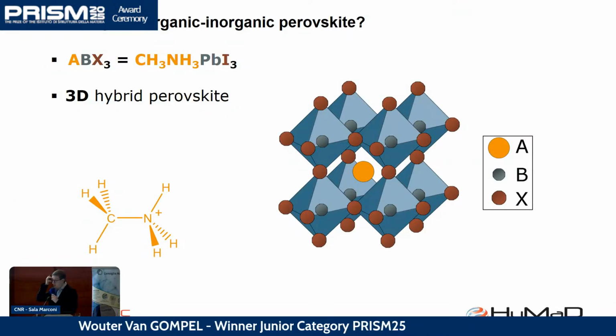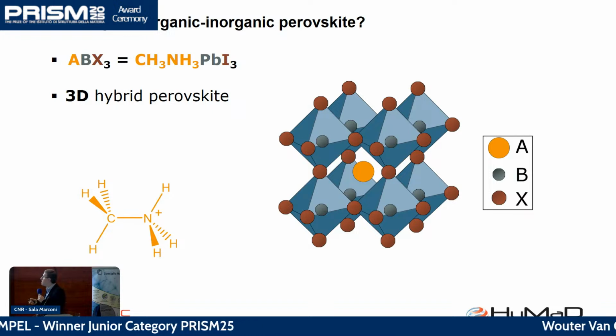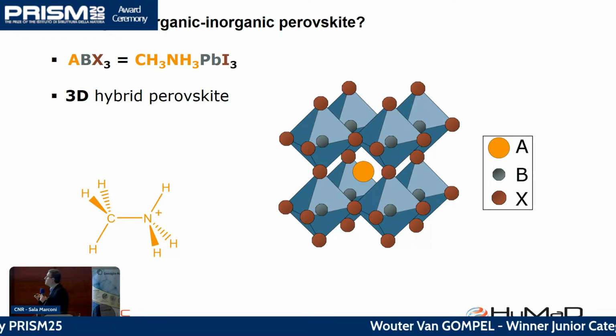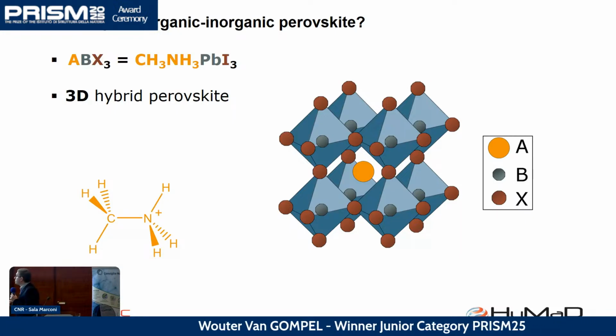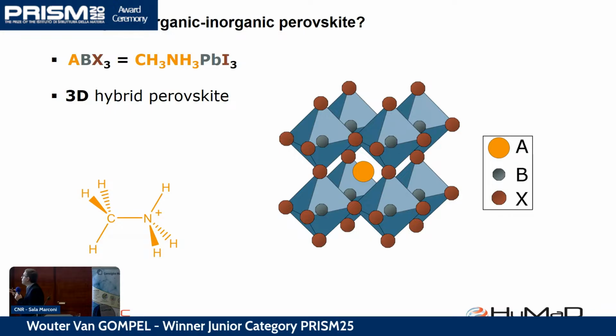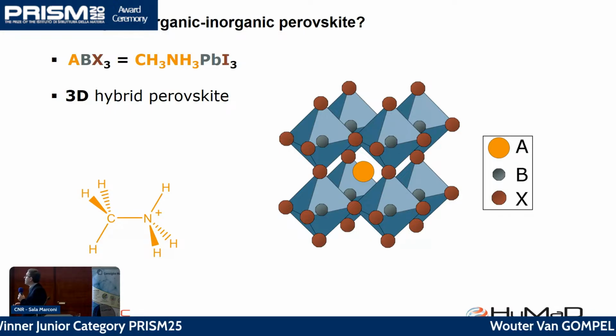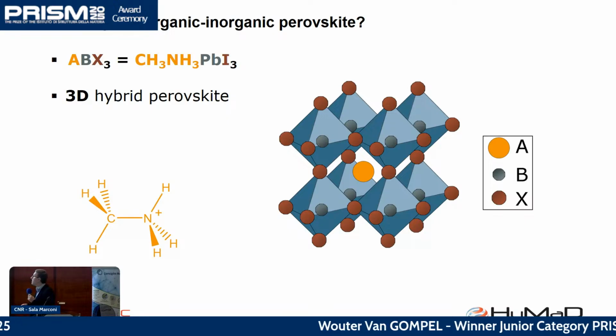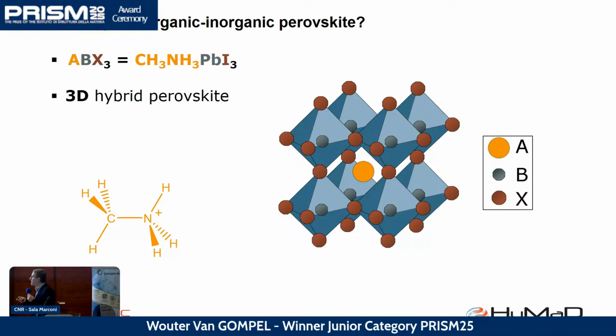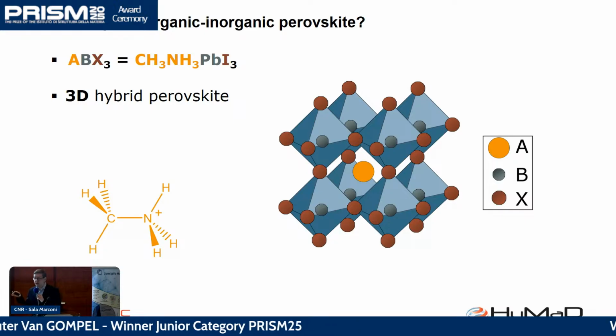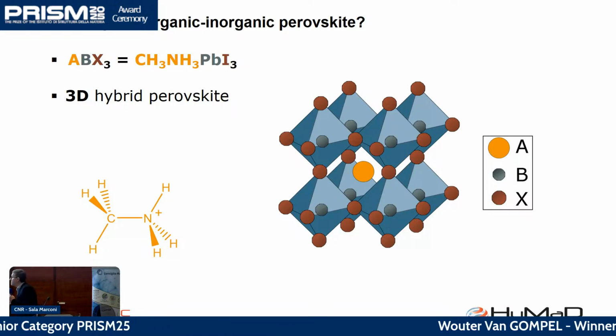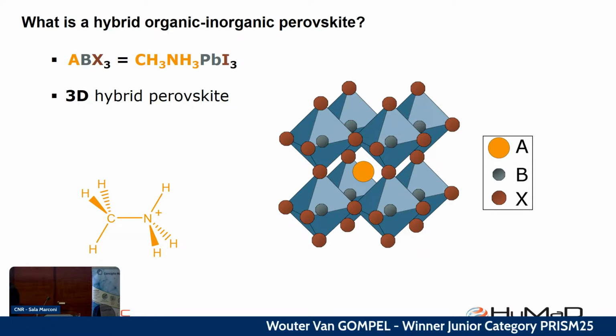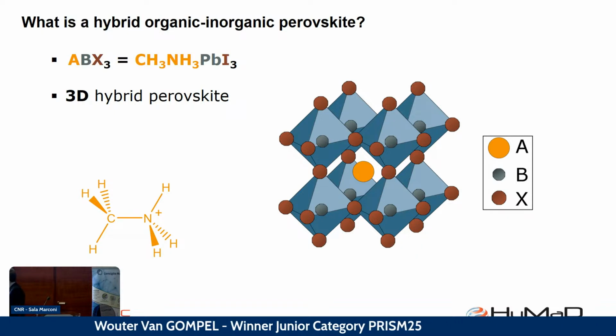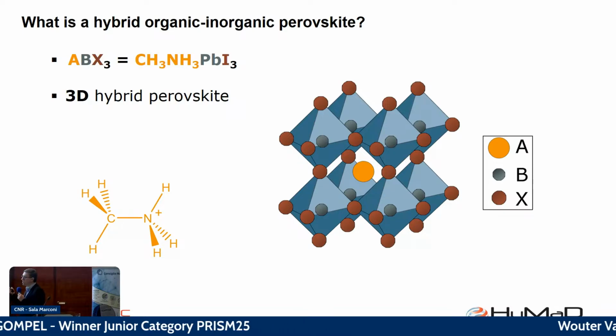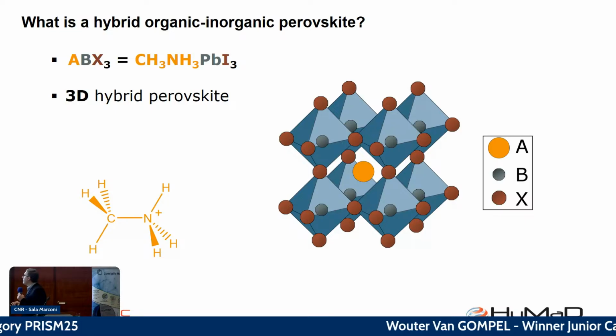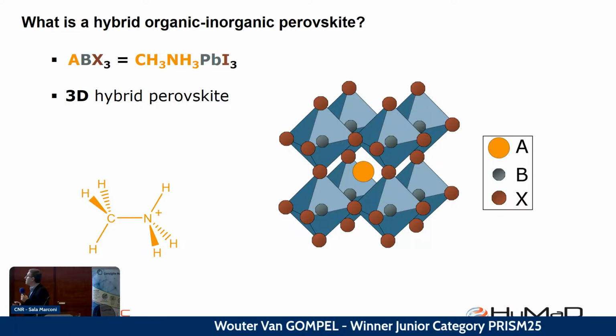So hybrid perovskites belong to the bigger class of perovskites. It's a very big class of materials which all share the same general formula, ABX3, with a well-known crystal structure composed of octahedra, with in general B metal ions inside of the octahedron, and then X ions at the corners of the octahedra, and in the middle you have a bigger cation, the A cation. In the case of the hybrid perovskites, the center cation is an organic molecule, typically an ammonium cation, like the methylammonium you see on the slide. And then the metal is typically lead or tin, sometimes germanium, and the X is a halide. So it belongs to the class of the metal halide perovskites.